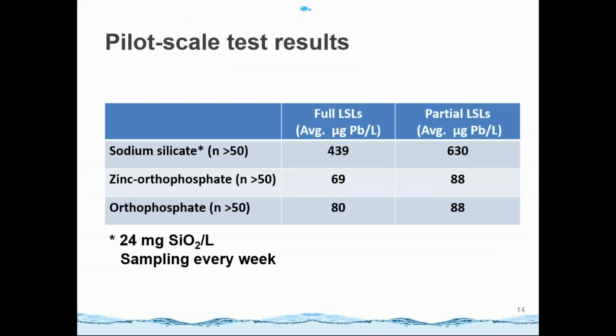So this is our preliminary data. As we can see, in the orthophosphate treated system, in the effluent from the full lead service line pipes, the lead concentration was in the range of 69 to 80 micrograms per liter. But at the same time, we observed a quite high lead concentration from the sodium silicate treated system, which was 439 micrograms lead per liter.